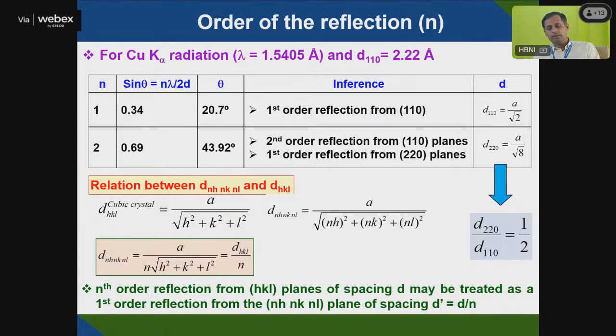And if you take the order of reflection, that I told n, that n lambda equals 2d sine theta, if you take here n equal to 1 for sine theta, with sine theta being 0.34 as the example I have given, the first order reflection plane of 110, you will get 20.7 degree. And the same second order reflection plane of 110, you will get 43.92. That will be the first order plane for 220, since the second order plane of 110 is equal to the first order plane of 220. So if you see the d spacing, d110 is a by root 2 and d220 is a by root 8. That means if you divide 220 by 110, you will get a 1 by 2 ratio.